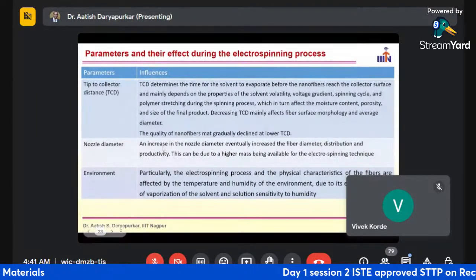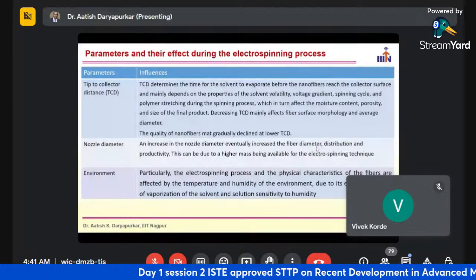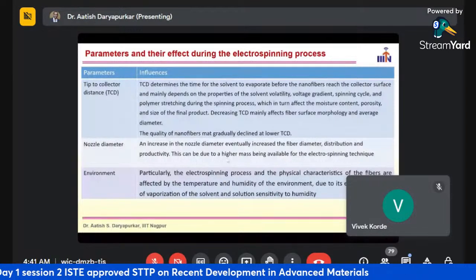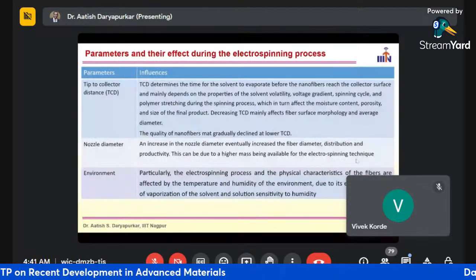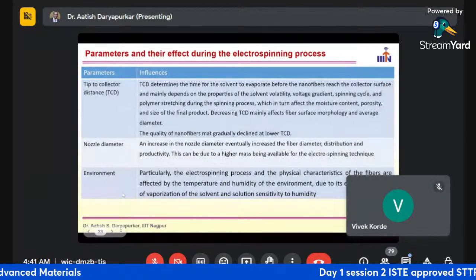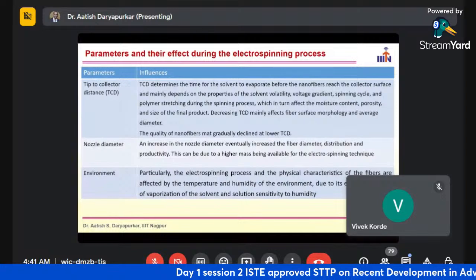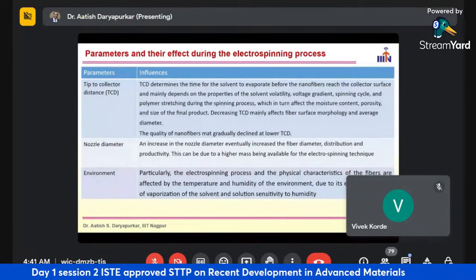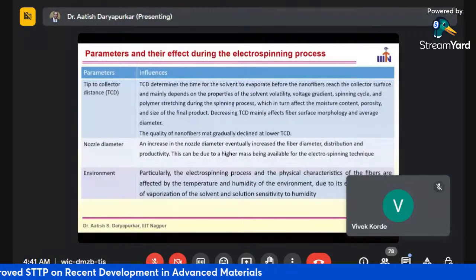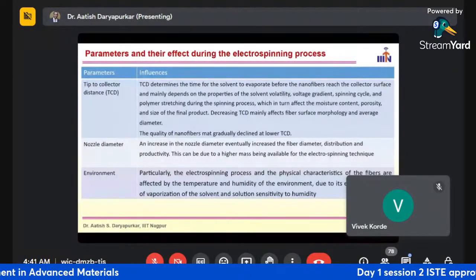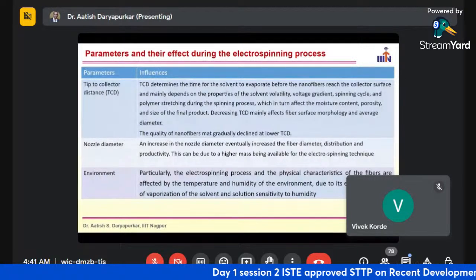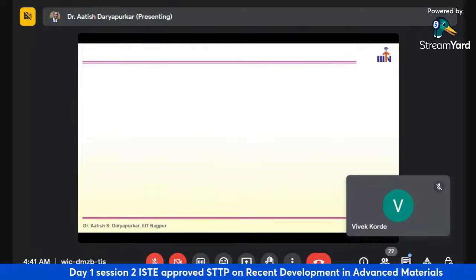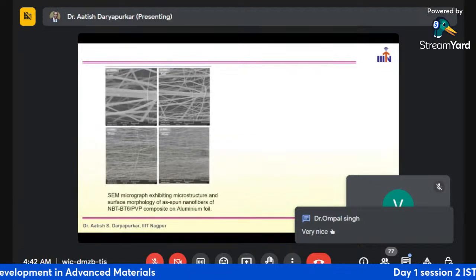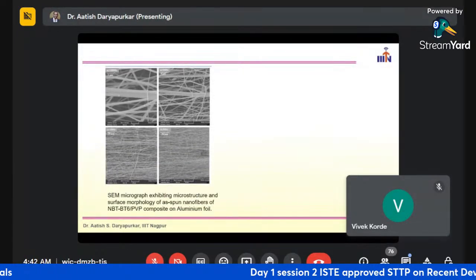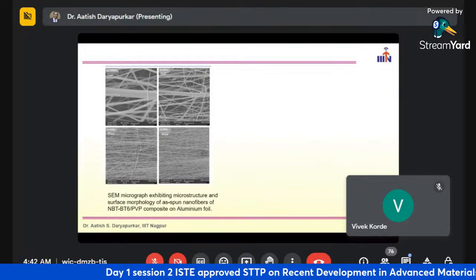Then nozzle diameter. An increase in the nozzle diameter eventually increases the fiber diameters, distributions and productivity. This can be due to the higher mass being available for the electrospinning technique. Then environment, obviously. For any chemical reaction or experiment, the environmental parameters are very important. The electrospinning process and the physical characteristics of the fibers are affected by the temperature and the humidity of the environment, due to their effect on the rate of evaporation of the solvent and the solution's sensitivity to humidity. So considering all these parameters, we were able to successfully synthesize the nanofiber of the sodium bismuth titanate, barium titanate compositions.